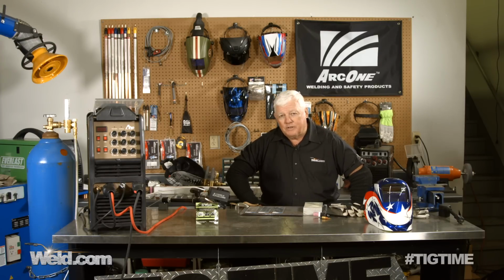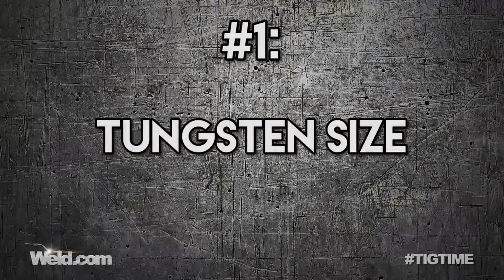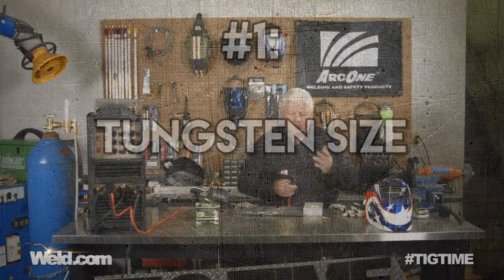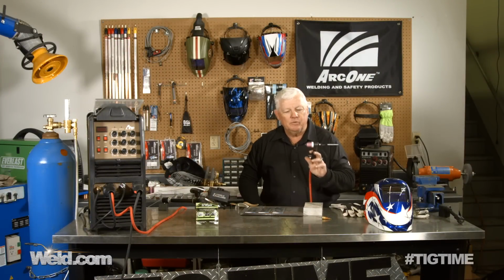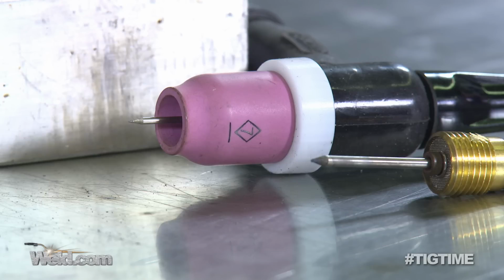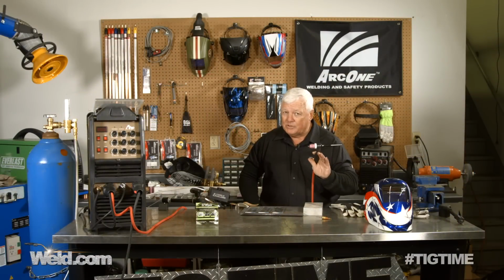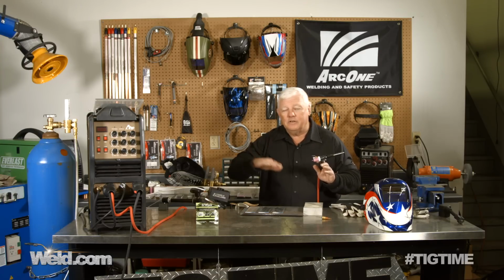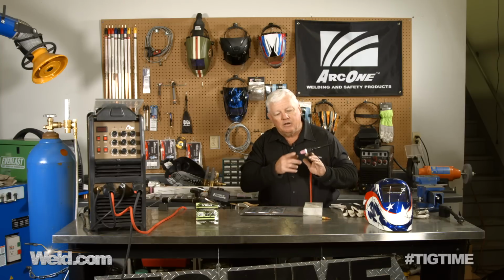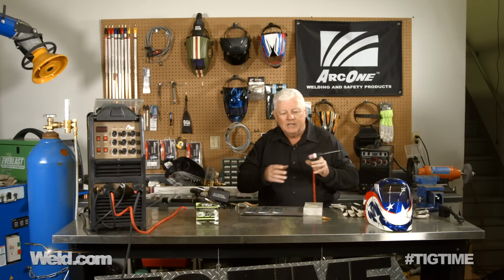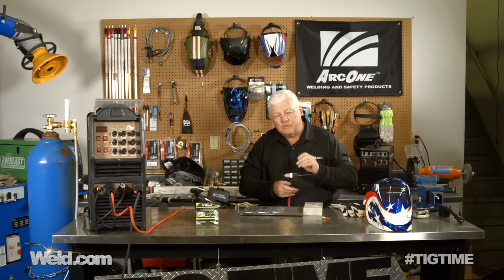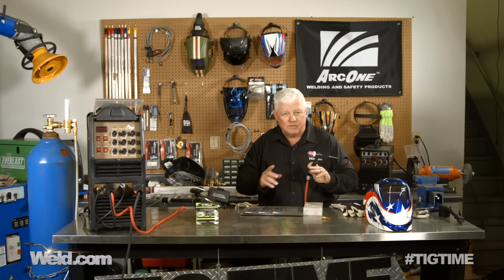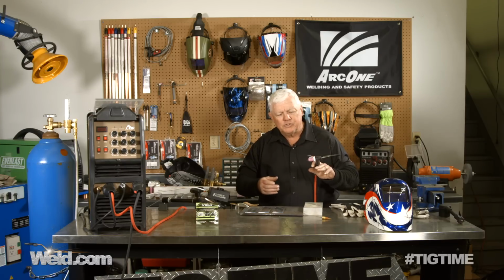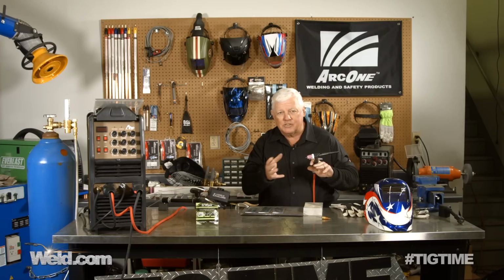I'm going to start off with the very first one: what size tungsten do I use to weld aluminum? Unfortunately, a lot of times if you're set up using 1/16 tungsten welding steel, you can weld up to about 120 amps before the tungsten starts breaking down. That's on DC minus. You hit the button to turn it over to AC, getting ready to weld aluminum, and all of a sudden this tungsten just explodes, or at least wears out or starts balling up and splitting. The reason is aluminum is not an efficient arc. You've got an AC arc, so the challenge on the tungsten is much, much more by far. As I reach that 120 amp mark, you're going to see this thing break down.